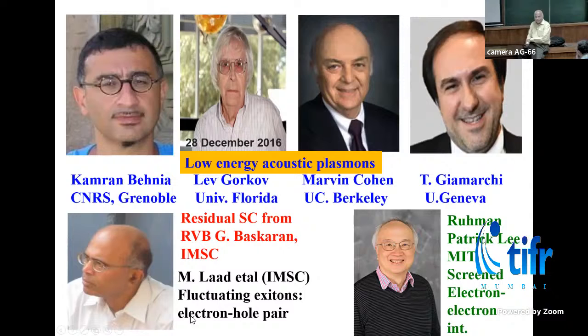There are many other people in this fray, about another 6 models. Gorkov, till his last breath, worked on bismuth, and in fact his last mail, before the day he died, said let's look at this afresh. Unfortunately, he's no longer there. And Baskaran, of course, has his pet model of residual superconductivity from RVB. Laad, you all know, is talking about a fluctuating exciton. Then Patrick Lee thinks it could be due to some Coulomb correlations which can give rise to an attractive interaction aided by the holes. None of these are able to fit the results which we have got recently. That's why I have requested Rajdeep to see where we can go to understand this.